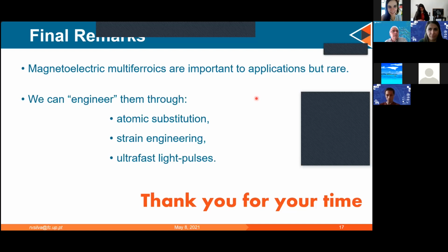What are the applications? As you said, there are applications, but they are rare. So what are those applications? At low temperatures, it's not so easy, but at high temperatures, like I said, if you have a multiferroic material, you can use the electric field to change the magnetic properties, and all our memories are based on magnetic properties, magnetic domains, magnetic memories, and if you can change them with electric field, it's much better. Besides that, you also can do magnetic tunnel junctions, but multiferroic tunnel junctions, where you can also control with electric field, or even exchange bias, multiferroic exchange bias applications for having, again, logic states with 4 parameters and mainly controllable by electric field.